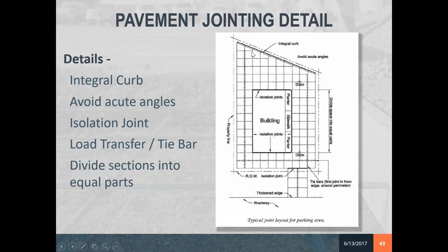You want to avoid acute angles. A lot of times we run these up and you get a little sliver up here in the corners. That's an immediate location for concrete to crack because there's not enough reinforcement in there or enough concrete to offset loading when it occurs, or just during the shrinkage when it's curing. So you want to make sure that you don't have any really tight acute angles. You want to come out away from the curbs or the edge of the pavement a couple of feet and then turn it back into it. And again, ACI has a lot of codes that lay out the requirements for this.